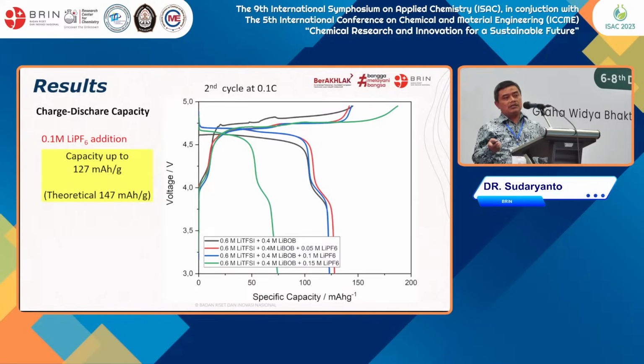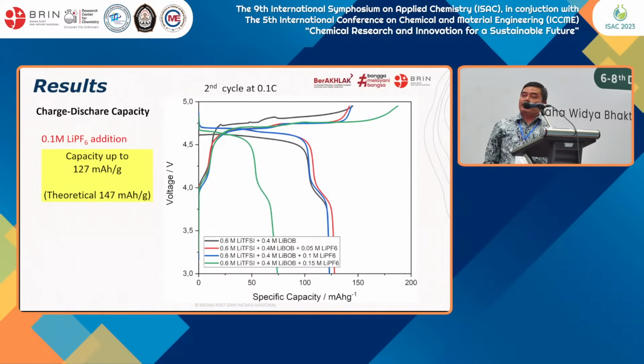When we use that electrolyte in a battery cell, assembled as a half cell using lithium metal, we can see that battery performance also depends on the type of electrolyte used. The addition of LiPF6 as an additive to the blended electrolyte increases the battery capacity closer to the theoretical value. We obtained 127 milliampere hours per gram, where the theoretical value is 147, which is more than 80% — acceptable for this battery system.